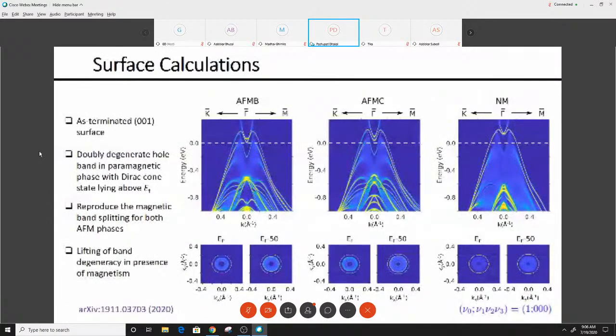In order to see if we can reproduce the change in band dispersion across the antiferromagnetic transition by theory, we also performed surface calculations for the As-terminated 001 surface. In the paramagnetic phase, a doubly degenerate non-trivial hole band crosses the Fermi level, forming a Dirac cone state lying above the Fermi level. Below the AFM transition, we can see both AFM-B and AFM-C give similar energy dispersion in the hole-doped region. However, above the Fermi level, the AFM-B phase realizes a type-2 Dirac cone, while in AFM-C we can see there is a clear gap in the surface states,